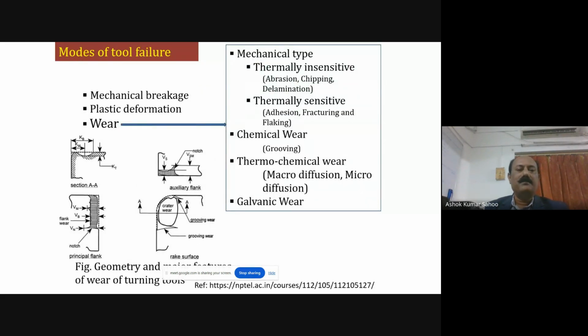And there are many forms and types of wear that occur at the cutting tool tip point during machining. One is flank wear, and then the crater wear. As we have observed, these are the patterns of wear seen at the flank tool rubbing interface zone, and also when the chip is flowing over the rake surface. So there is crater wear formation due to adhesion and diffusion mechanisms, and also there will be a very small contact between the auxiliary cutting edge point and the work surface. So there is an auxiliary flank wear also.